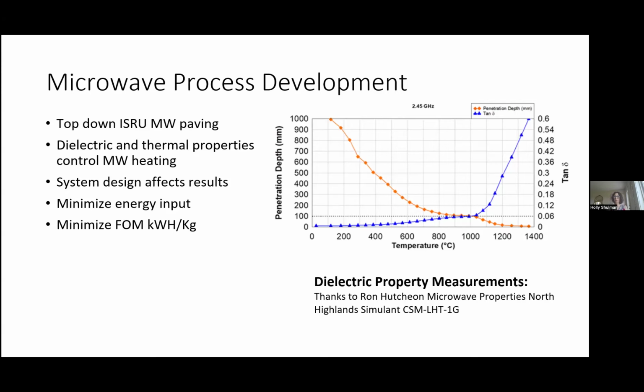You're actually heating in a conventional way and then dropping it into a low field microwave. And so these were too high temperature. And the things I want to point out here: on the left, I'm showing penetration depth, and on the right, tan delta. So the blue line is tan delta. Tan delta is a measure of the heating through dielectric loss, and penetration depth is how deep those microwaves are penetrating.